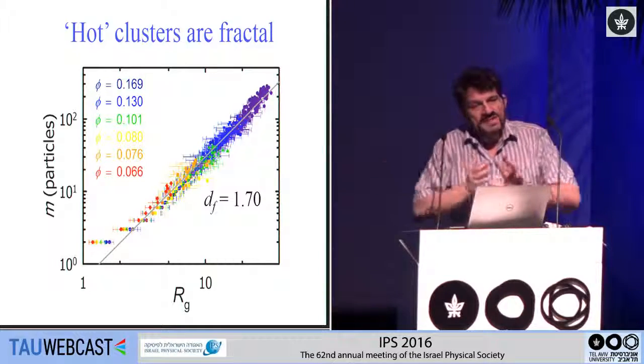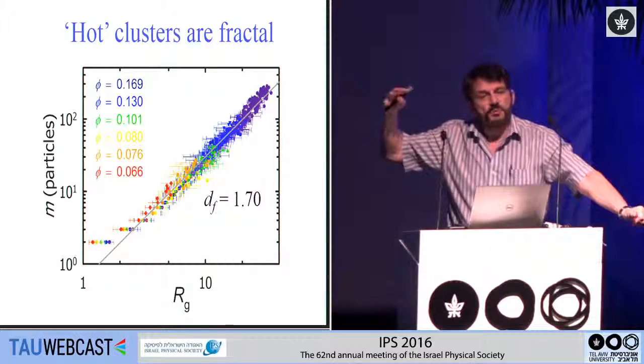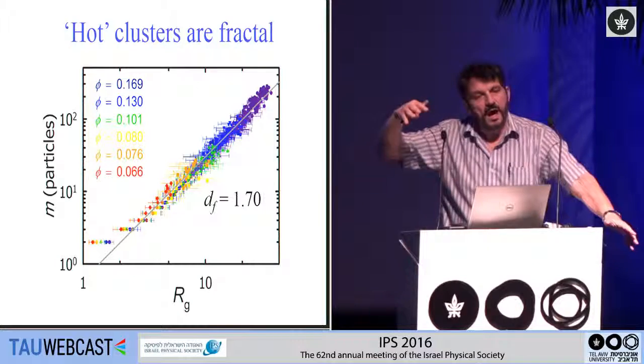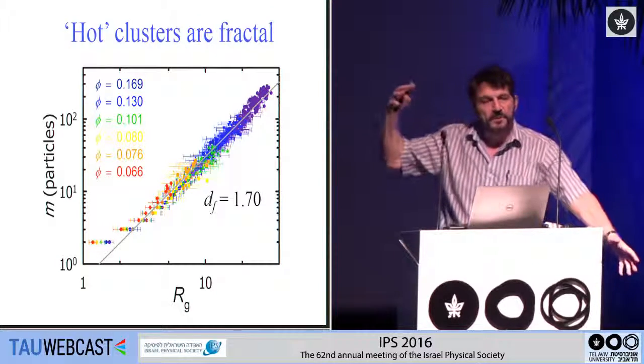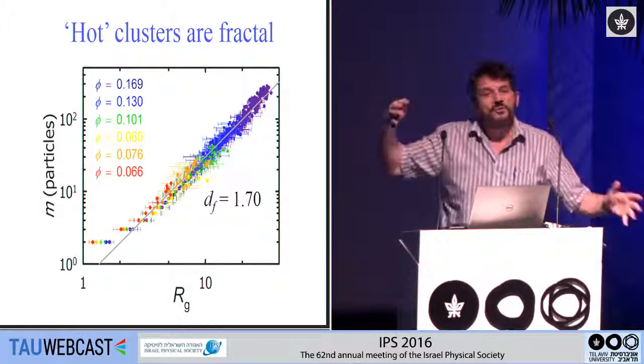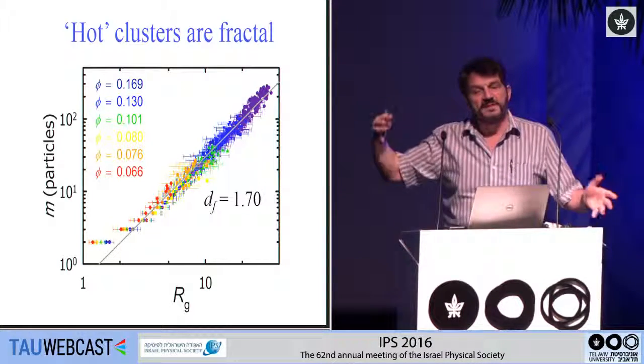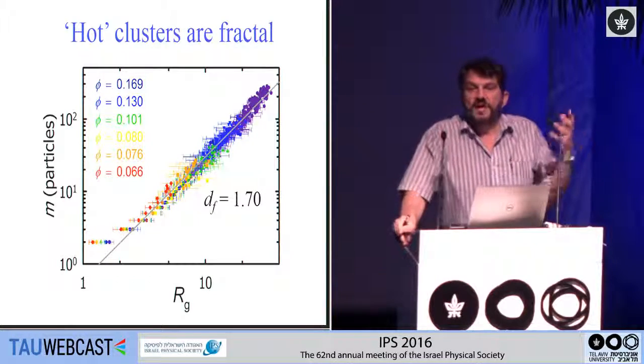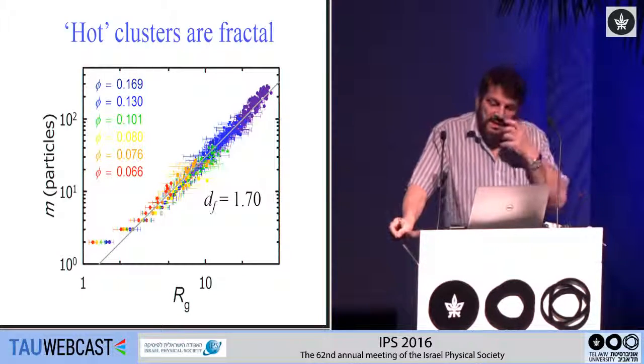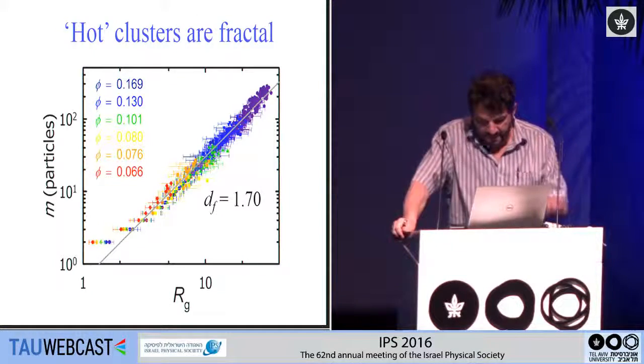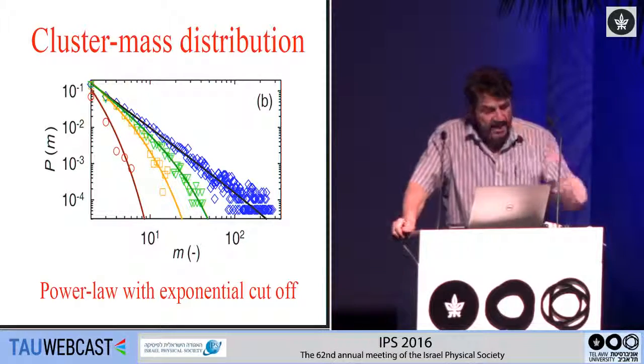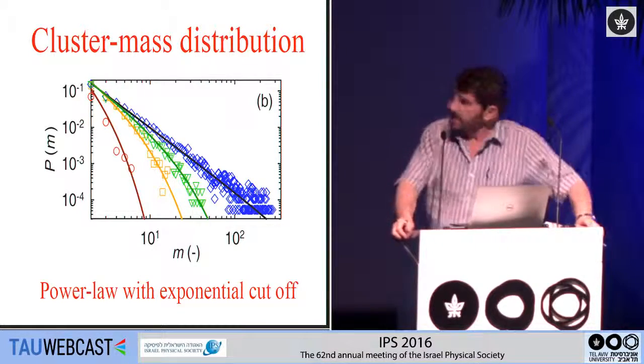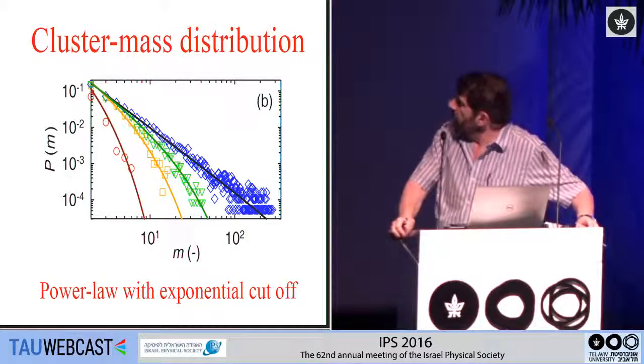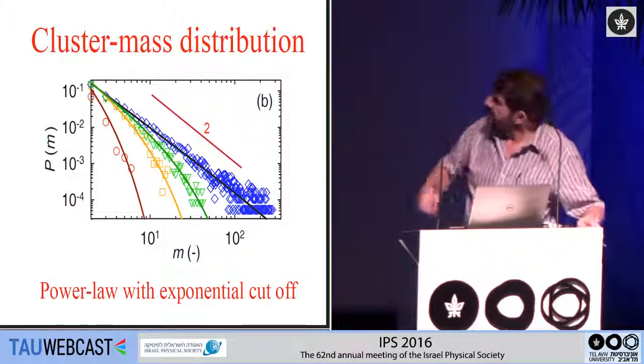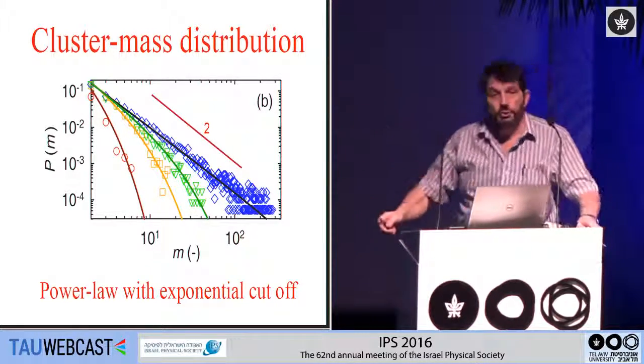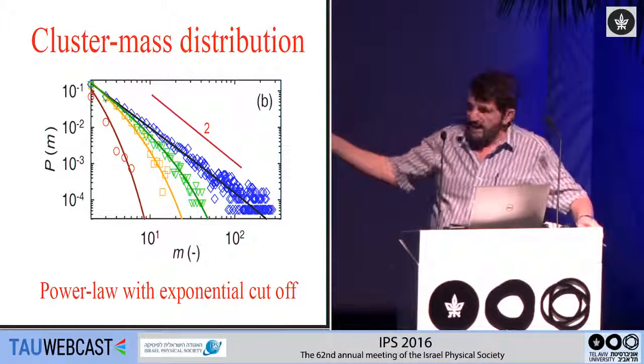That means that you can fill space with these highly superheated particles without using all the particles. You can nevertheless fill space because these are fractal in nature. They extend much larger than their mass would demand or would allow. And you can look at the distribution of these particles, and you see that there's a power law distribution. The power law exponent is 2, and there's an exponential cutoff.